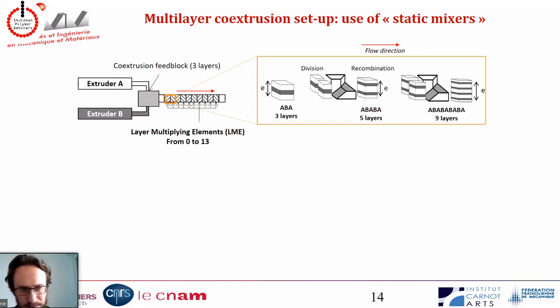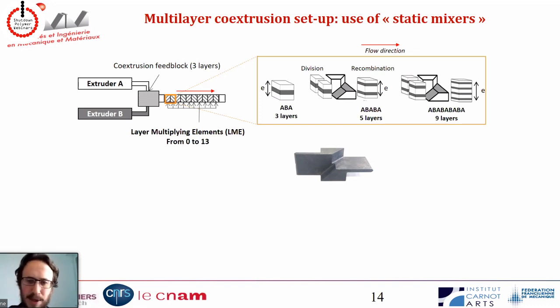So what will I do? I will do simply this. It's actually quite simple. I put my two initial extruders with a feed block. So I have my 3 layers film and I'm still in the melt state. So instead of going out to cool it down and have my final film, I put this polymer flow in a channel, still under high temperature, so it won't cool down. And I use multiplying elements, which are these little elements. It's little pieces of steel that look like that. It's a couple centimeters long, couple centimeters high.